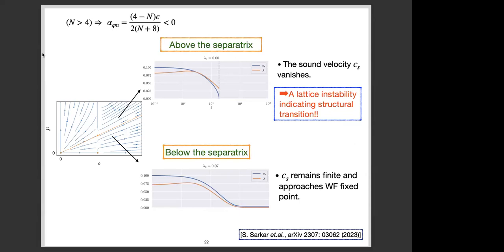of the parameter. But below the separatrix, for example, where we are here, we again plot the sound velocity and lambda, the elastic constant, with L, the RG scale. And what we see is that lambda actually goes to 0 asymptotically. So basically we have a stable Wilson-Fisher fixed point here, and that's why lambda flows towards 0. But the sound velocity remains finite. So in this regime, there is no lattice instability or first order transition, as it remains finite for a sufficiently large RG scale. So that's quite different from the n greater than 4 case, basically.